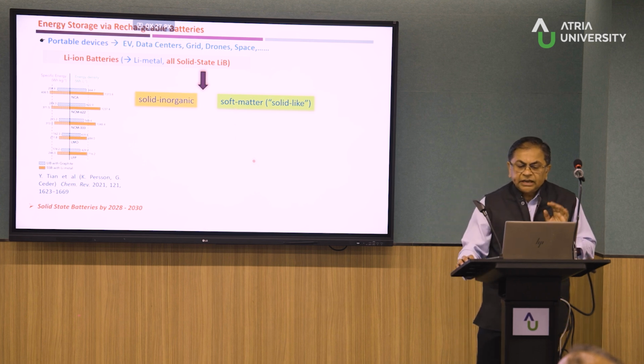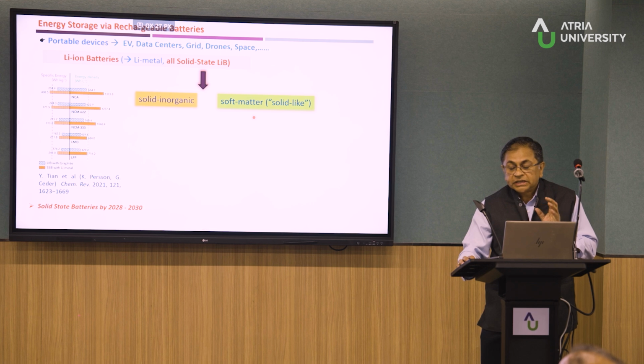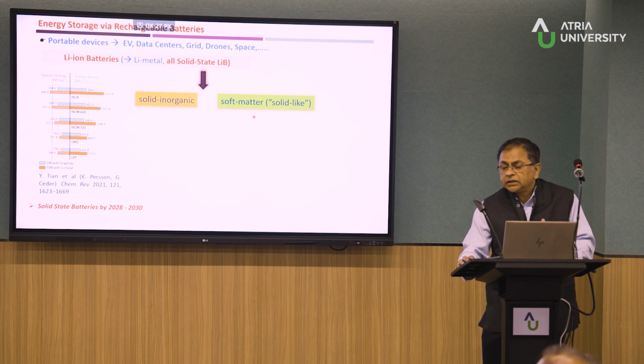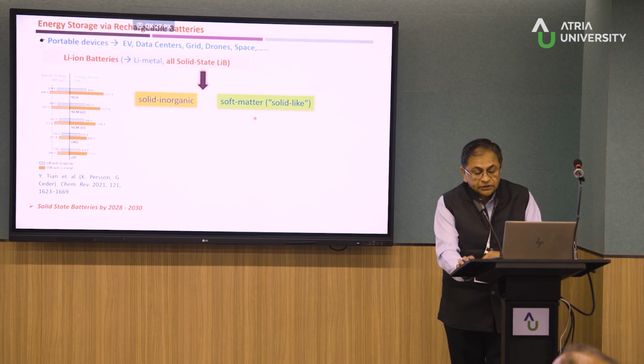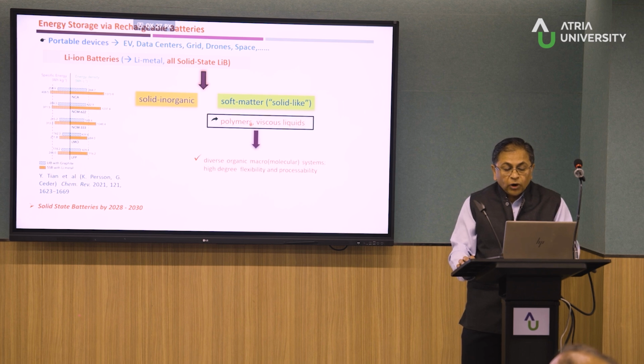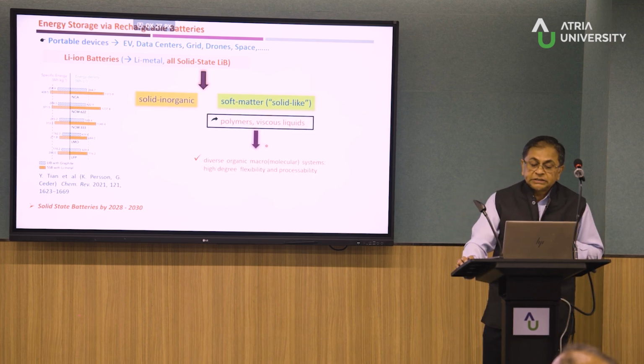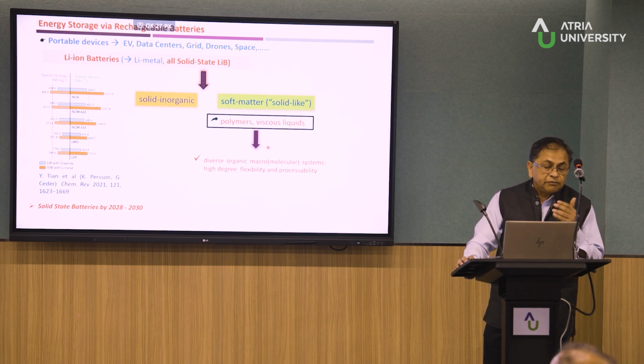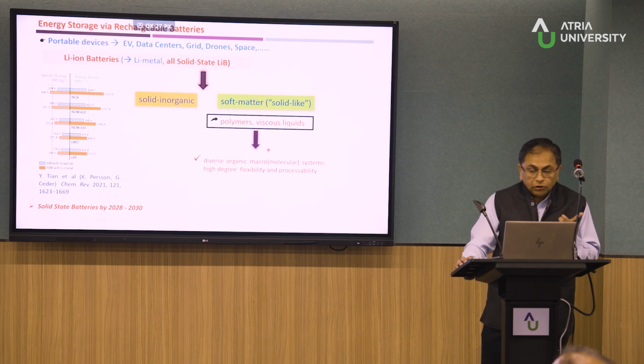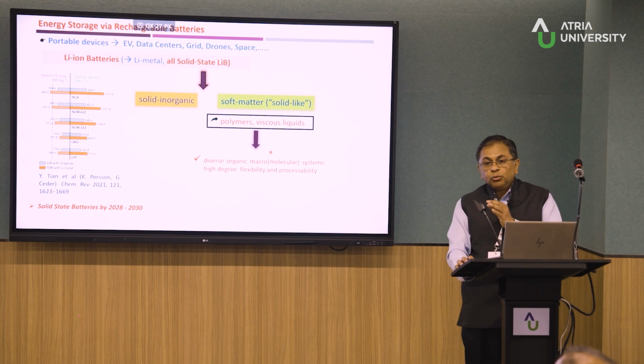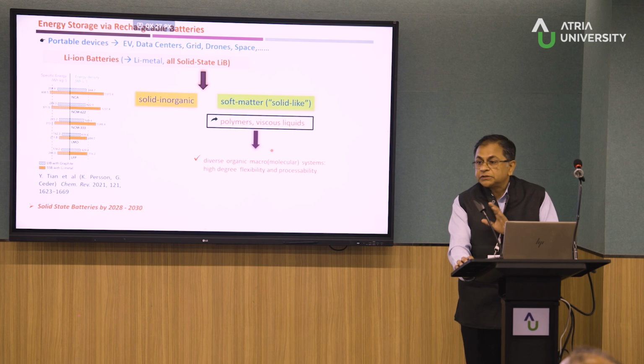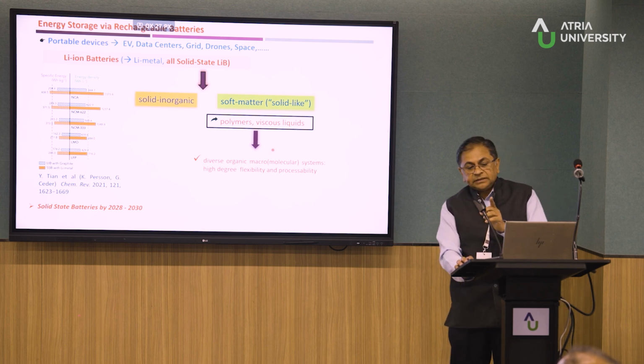But looking at the strength of our lab, we have been actually working on soft matter systems. These are so-called solid-like systems. Okay, their conductivities are lower than that of a liquid electrolyte, but the mechanical properties are better than that of a liquid electrolyte, but not as great as a solid system. That is where typically these electrolytes lie. Examples of soft matter are polymers or viscous liquids. And why we are interested in them is because of the diversity these systems can provide in terms of composition. You can play with the macromolecular structure, and the most important thing, which is a big drawback with inorganic solid electrolytes, is the processability. Very severe restrictions on the processability when it comes to implementing into a device. That's the big problem.